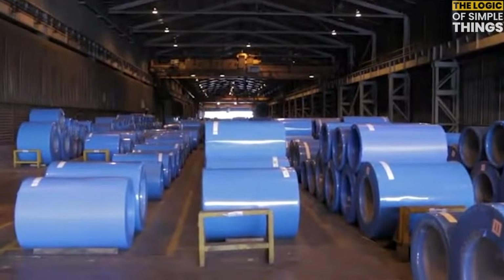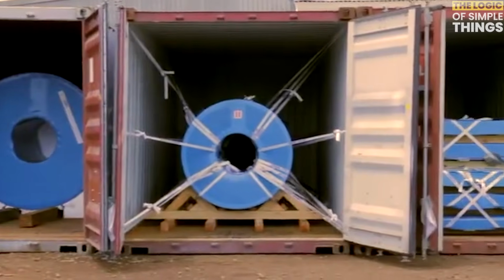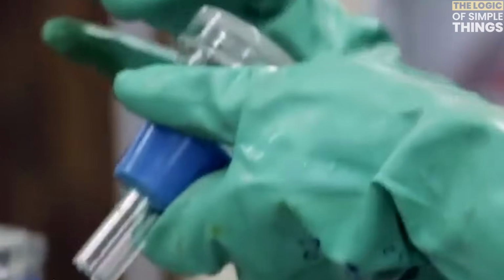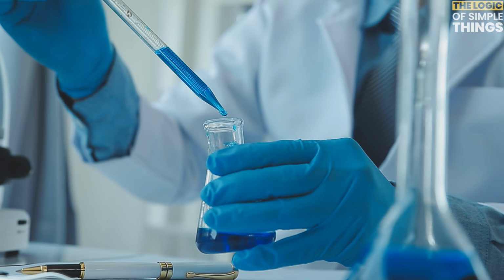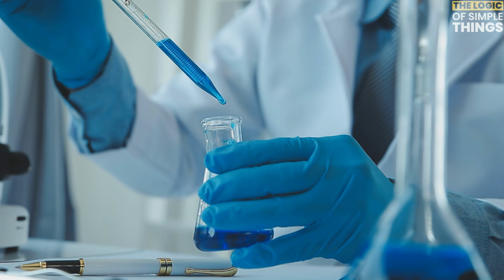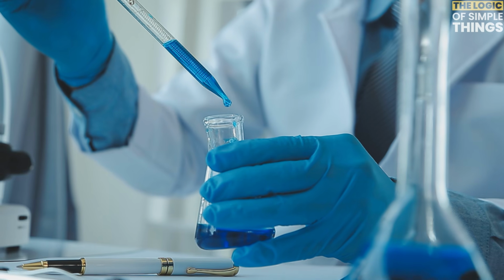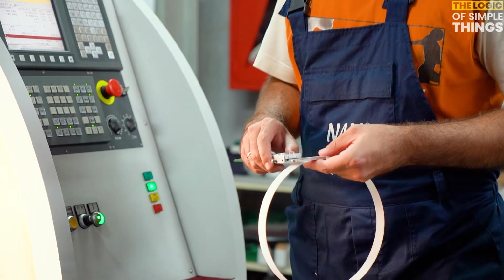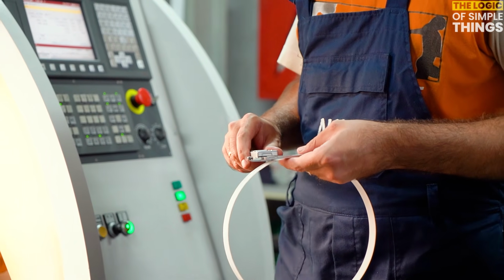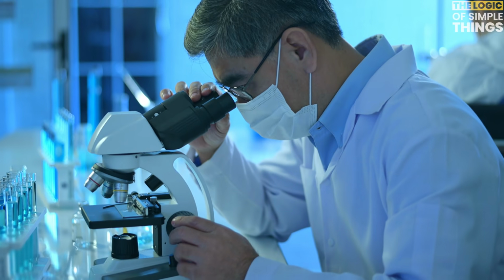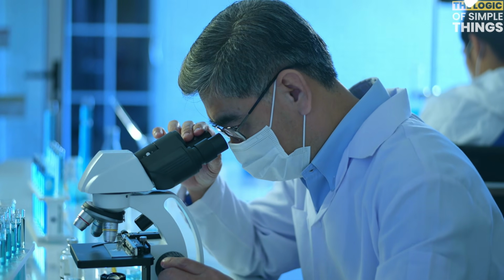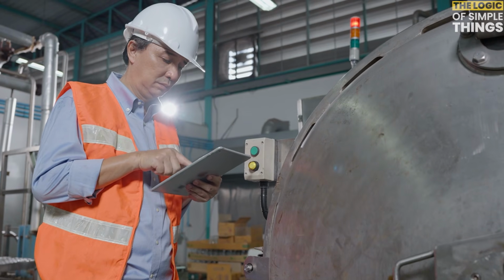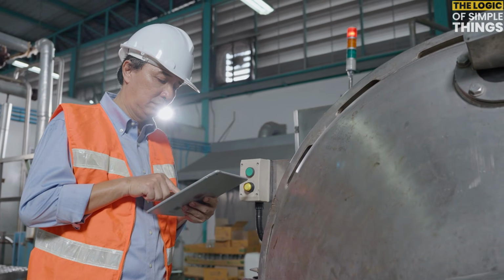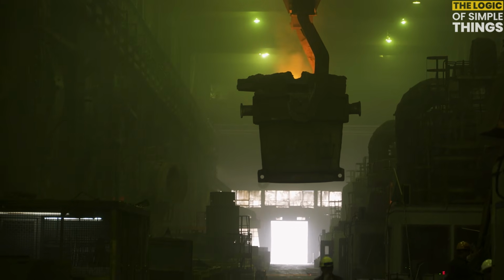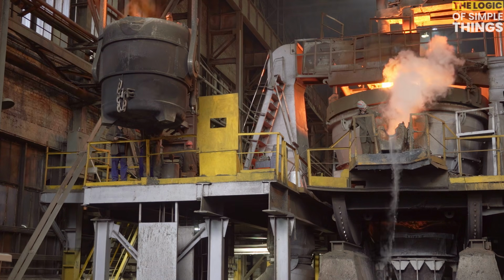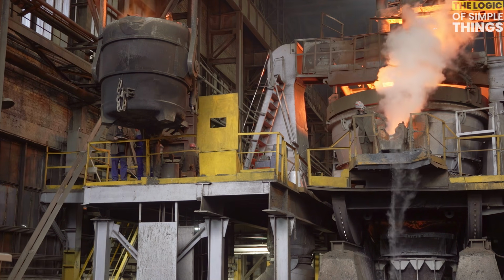Before any of this steel leaves the factory, it has to run a very strict gauntlet. Quality control teams take samples at virtually every stage of production. These samples are subjected to chemical analysis to verify the exact composition, every element, down to hundredths of a percent. They undergo mechanical testing: tensile strength, hardness, and flexibility. They're examined under microscopes to check the grain structure and hunt for any microscopic defects. Only steel that passes every single test earns the right to move forward. A batch that falls short doesn't go to a customer, it goes back into the furnace. Nothing is wasted, and more importantly, nothing substandard reaches the world.